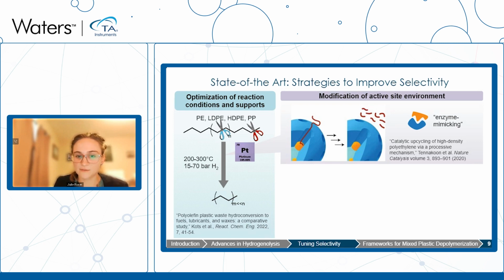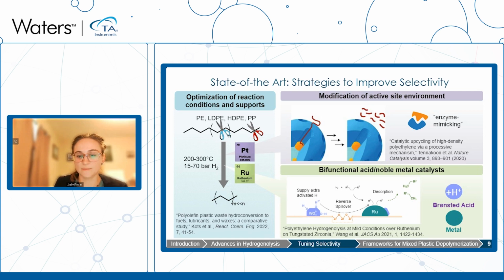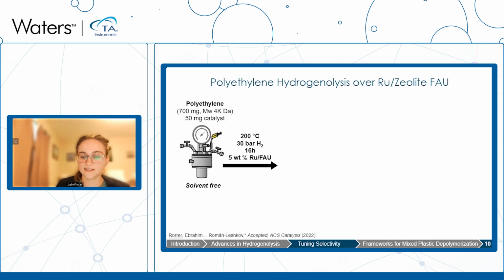Another method is to employ bifunctional acid and noble metal catalysts. And this can be done with platinum or ruthenium, as I'll show you, where you have a Bronsted acid and a metal that work cooperatively to actually shift the mechanism to a hydrocracking mechanism to improve selectivity towards liquid products. And so what we wanted to do was investigate a type of bifunctional metal acid catalyst using a zeolite support.